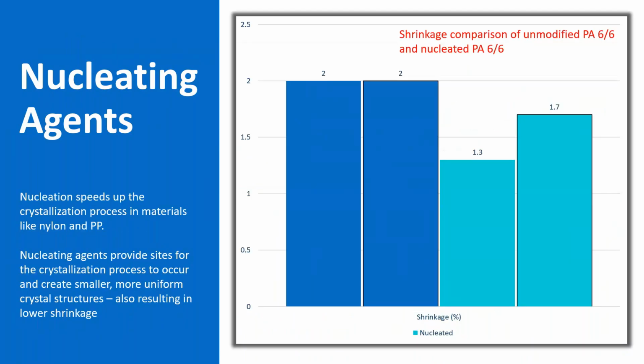The other thing to note, not only is it going to make it so you crystallize sooner, it also crystallizes faster. Essentially what it's doing is it provides little sites for the crystallization to start to happen around. And so there's more of those sites now available. So it happens faster, and it creates smaller, more uniform crystal structures across all of those new sites that have been introduced by the nucleating agents. And with more uniform crystal structures, you also end up shrinking a little bit less, because across the whole thing, there are a lot more sites to crystallize across more uniformly. So you end up with a little bit lower shrinkage.